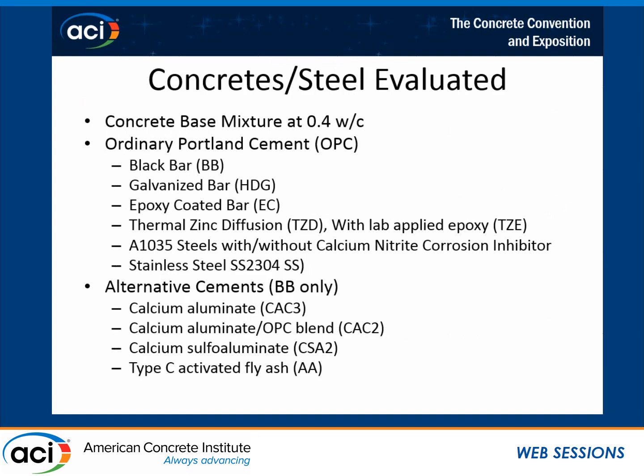So for the concrete and steels, we looked at concretes with a base mixture of 0.4 water-cement ratio. The first study was using ordinary Portland cement. We looked at black bar, and you can see the initials if you see something later on. Black bar, galvanized, hot dip galvanized, epoxy coated bar. We looked at a thermal zinc diffusion coating and also a lab applied epoxy. 2101 and 1035 steels with and without calcium nitrite corrosion inhibitor, and a duplex stainless steel.